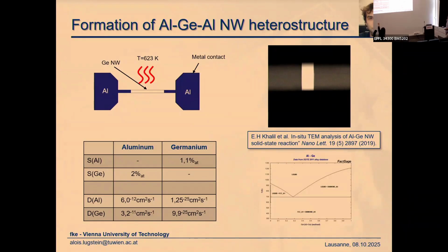You said in that image, I forgot the panel D, when you have a very thin layer, at that point the aluminum is crystalline, when it's really thin. Is it the width? The width, yeah. I mean, the way you were shooting, right? It was thick, and then the width, not the length, but the width. So at a certain width, it becomes single crystal. Below 500 nanometers, yeah. So the grain of aluminum is typically in the range of 1 micron. So as soon as it gets smaller than that. But then that reduces the detectivity, so that's why you prefer to have somewhat wider detectors.